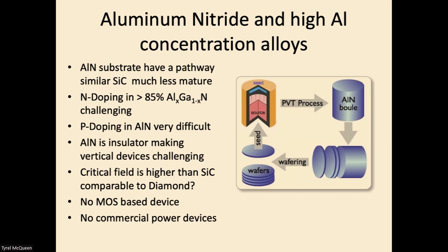GaN, with the new substrates, will try to get vertical devices. The critical field is higher than silicon carbide and comparable to diamond. And I put question marks because I told you earlier, until you actually measure it, it's just speculation. There's some questions about diamond actually, and people are trying to measure that because it doesn't seem to live up to some of the hype on the critical field. And also no MOS-based device technology. I am not aware of any commercial power devices based on aluminum nitride or high-X aluminum.